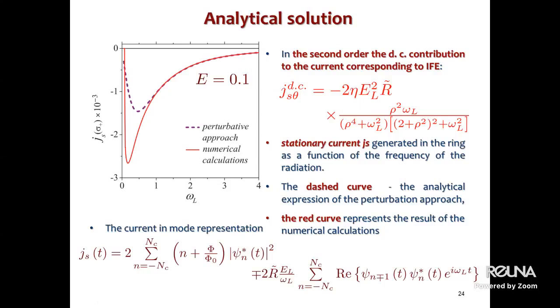However, it shows marked discrepancies for lower frequencies. That is, when the effective amplitude ratio E divided by omega becomes large. Our small parameter is the amplitude parameter E divided by omega. When omega is small, since it's in the denominator, this parameter becomes large. That's why for that case, a perturbative approach does not show the correct result.